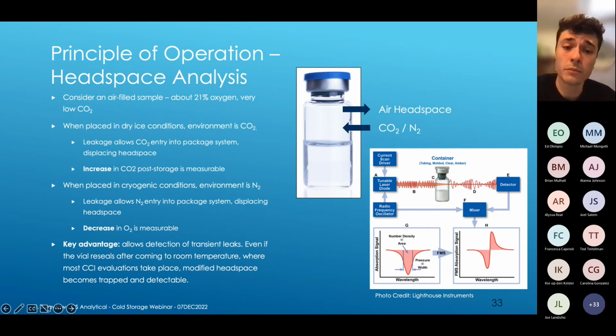Similar setup for samples placed in cryogenic conditions, except in this case, the environment is nitrogen. And so we're replacing the air headspace with nitrogen, and a decrease in oxygen is what we're measuring. A decrease in oxygen from about 21% downward as a result of nitrogen replacing that headspace is indicative of leakage.